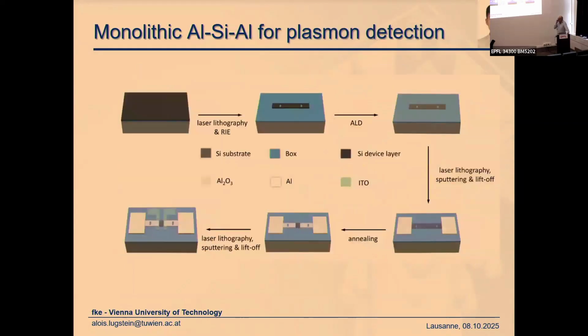That was again the point where we intended to make use of that for plasmonic devices, and Zhao modified the process in a way that he just patterned holes into these sheets before the aluminum deposition. And when you then do the exchange reaction, these holes, which were formerly situated in the silicon, are then situated in the aluminum. That works quite fine.